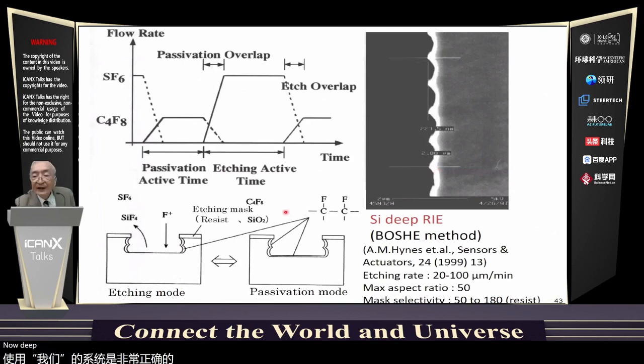The deep RIE system widely used now is this Robert Bosch method. SF6 gas for silicon etching and C4F8 gas for passivation are supplied alternately. High etching rate and deep etching are achieved at room temperature.